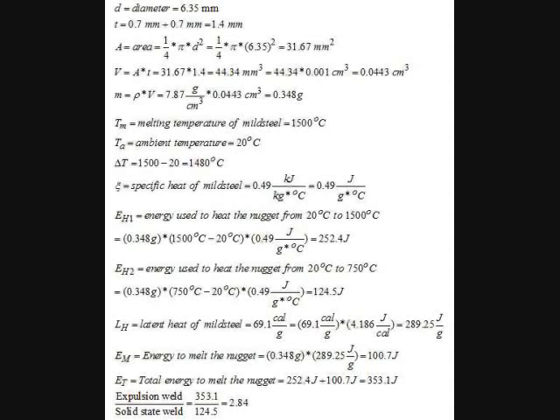Energy used to heat this from 20 degrees C to 750 degrees C, which is the coalescent temperature, is only 124.5 joules. Okay? Latent heat of mild steel is 69.1 calorie per gram. We convert it, it comes out to be 289.25 joules per gram. So this calculates out to melt the whole nugget takes 100.7 joules. I add up the 100.7 to the 252.4 joules. I got 353.1.